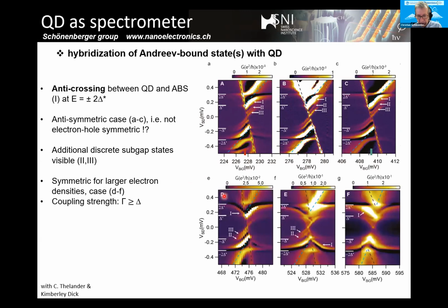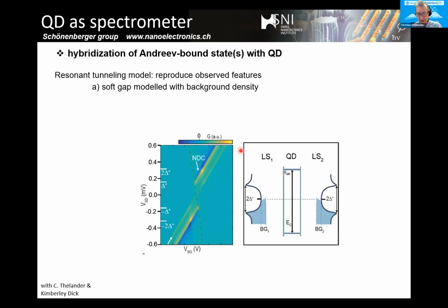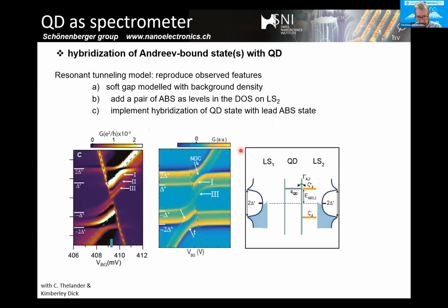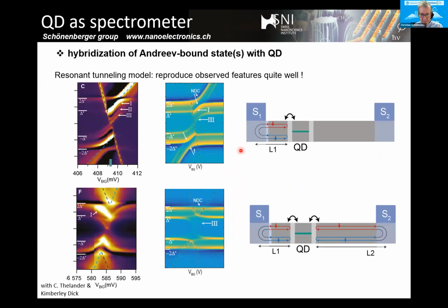All right, so when you increase the gate voltage, all of a sudden you see an Andreev bound state coming also from the other side, and it starts to anti-cross with the dot state. Again there are a couple of features inside here, but it looks much more symmetric than it does here. It's quite asymmetric in this picture, and the way we can understand this is quite simple. Maybe I just don't show a model, because time is running out. Let me just try to explain what happens. In the beginning, when you are above pinch-off, because this section is short, there is at some point an onset of superconductivity appearing here. The Andreev bound state forms on the left side. This becomes kind of the short junction limit, and then you see this Andreev bound state interacting with the dot level. That gives this asymmetric looking feature.